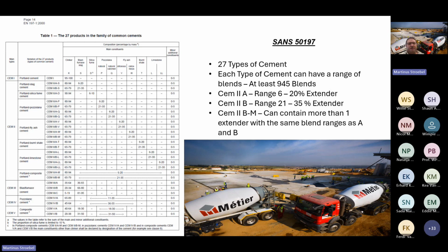A CEM II A, we can blend anything from 6 to 20%. That is typically the cement that we would get. And as a ready-mix supplier, you would extend further to produce the most cost-effective concrete on the market, which is technically sound. And with every percent of ash or fly ash or lime extender, you change the rate of gain, and it influences what is possible on site. The same with the Bs, you can go up to a 35% extender, and if you go into a B mix, you can even complicate this more because you can add more than one extender into that cement.